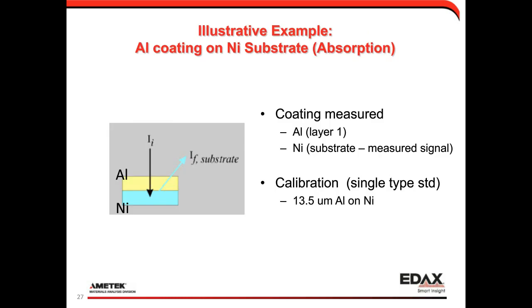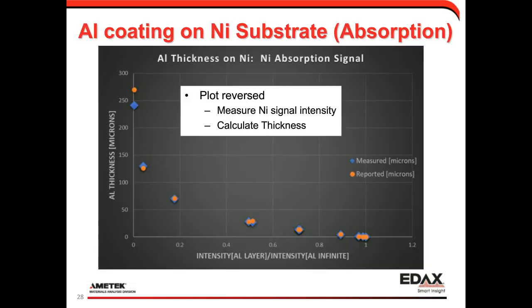Okay, now we're going to take the same samples that we measured in emission mode and we're going to measure them in absorption mode. And now I switched over to calibrating with a slightly thicker aluminum foil because our measurement range is going to increase. So here's the plot now in absorption mode. So now we're not measuring the aluminum signal directly, we're measuring the nickel signal coming through the aluminum substrate. And we've got our intensity ratio on the x-axis, our thickness calculation on the y-axis. Our range that we're plotting up there is up to 300 microns. Our orange circles are the reported values. Our blue diamonds are the measured values.